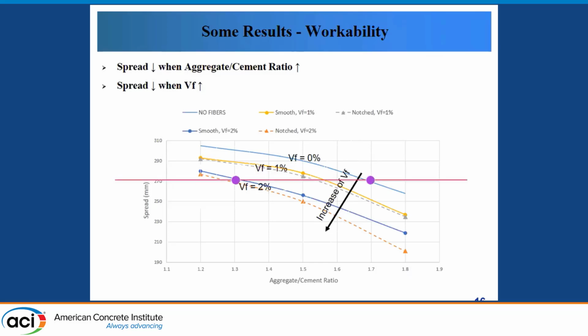For example, if you would like to have 270 millimeter of spread, the aggregate cement ratio should be 1.7 without having any fibers in it. But if you want to add 2% of fiber, then the aggregate cement ratio should be limited to 1.3 and still achieve the same spread value.